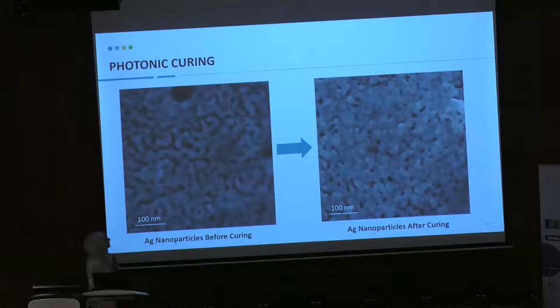Here we have SEM images where we have silver nanoparticles, which is the ink we are using to print the patterns, and they are not fused well. When we hit them with 2 flashlights, they are fused and they are creating the conductive path.